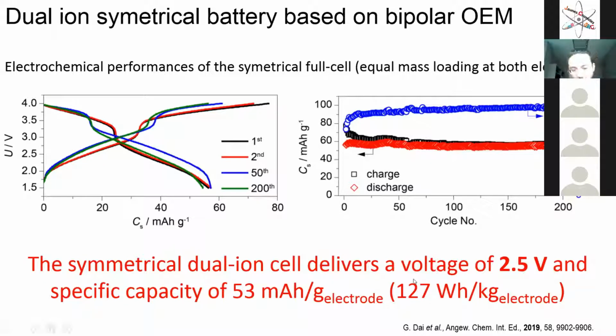So this symmetrical dual ion cell delivers a voltage of 2.5. As I said, it is a good voltage for organic batteries, but the challenge is the specific capacity is still a little bit low, 53 milliampere hour per gram. So the research here is trying to increase this capacity and a little bit increase the voltage, and by combining this, you will end up with a high energy density.